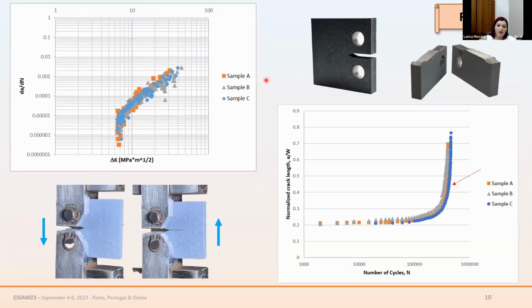And here are the results. We saw from this crack propagation rate versus stress intensity that there was no particular difference between all of these three components analyzed, and the results are similar to each other. While regarding the normalized crack length versus the number of cycles, we saw a small difference for sample C, which seems to have a greater resistance to crack growth propagation, but also in this case, this difference is minimal.